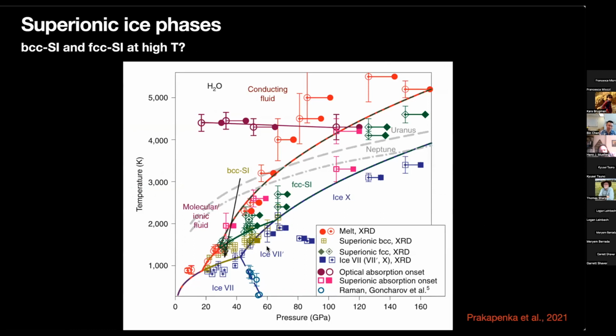And the ice phase diagram is actually pretty complicated. The most recent work shows that there may exist a superionic phase. If there is a superionic phase, that would indicate there may be a kink in the melting relationship with pressure. That means the ice would melt at a higher temperature than if we extrapolate from the lower pressure data.